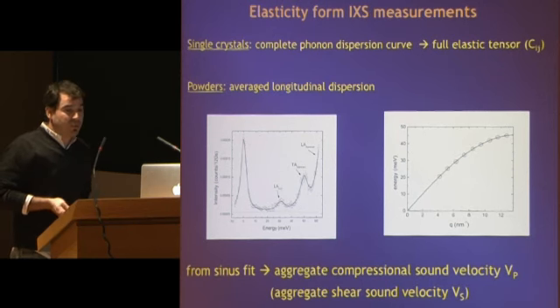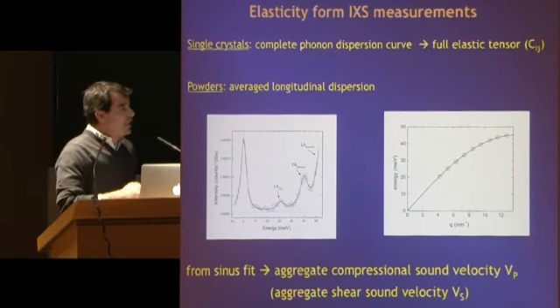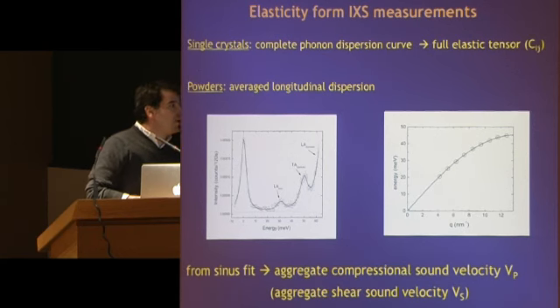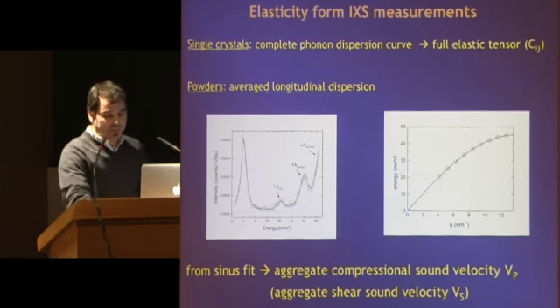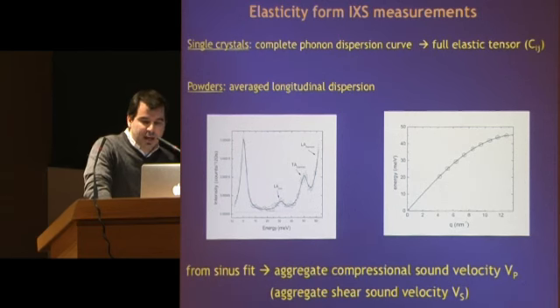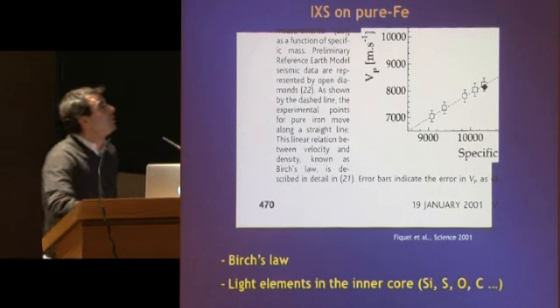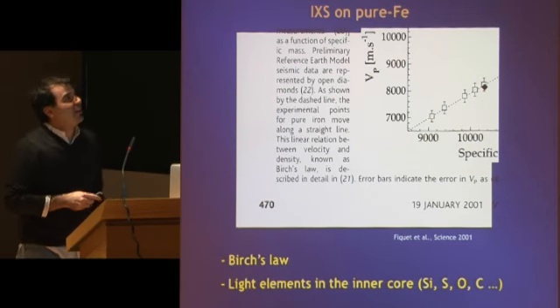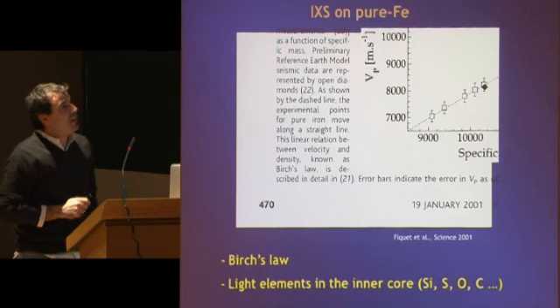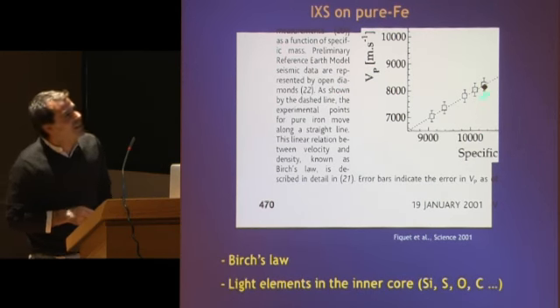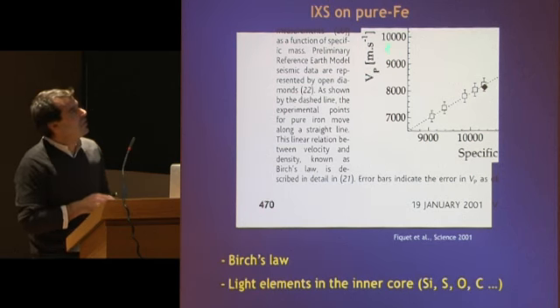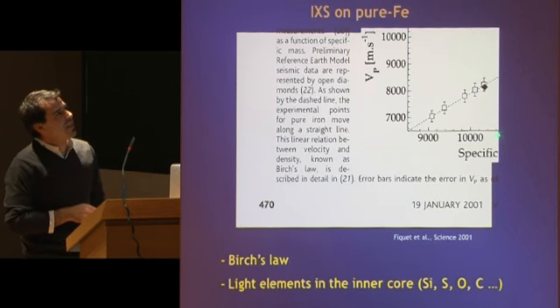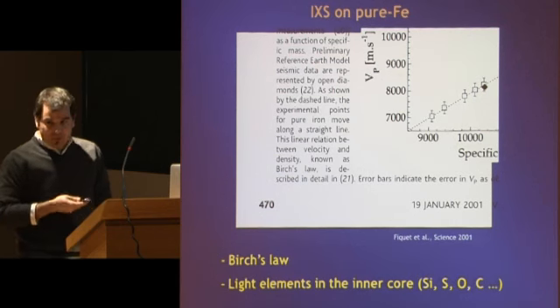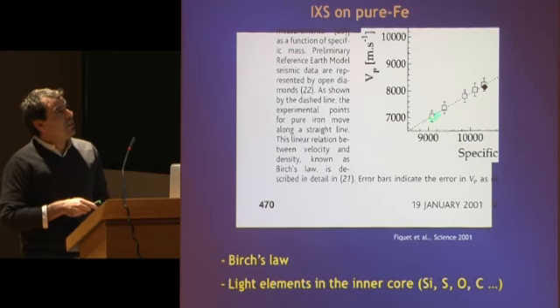And then if we use a bulk modulus, as for example determined from diffraction, we can get the shear velocity as well. So with this in mind, we can go back to another problem and look at inelastic X-ray scattering on pure iron. Here you can just see a little bit of what I wanted to show. That was the compressional velocity as a function of density. The inelastic measurement under static conditions by IXS are these open symbols.